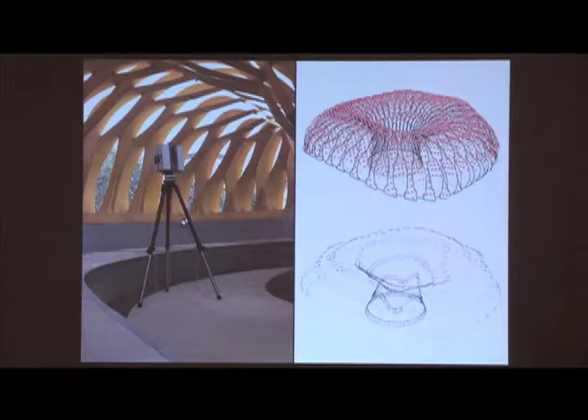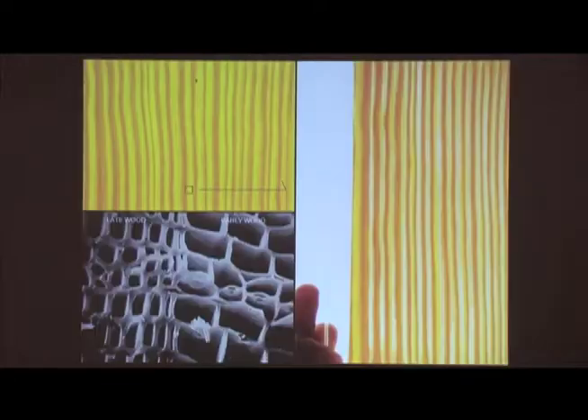And we were very pleased to see that, first of all, when it was built, the form found on site was incredibly close to the form that was found with our computational design process. And even over a couple of months with a lot of humidity cycle changes, it kept that inherent tension. We're also working on a number of ways of intervening with wood on the microscopic level.